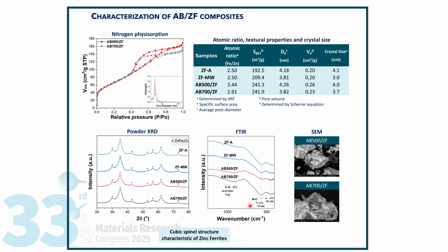FTIR analysis also confirmed the formation of ferrites, showing signals at 570 and 433 per centimeter, corresponding to the metal-oxygen bond in the tetrahedral and octahedral sites, respectively. In addition, a signal was observed in the composites around 900 per centimeter, due to the incorporation of activated biochar. On the other hand, SEM images show the incorporation of ferrite around the activated biochar.